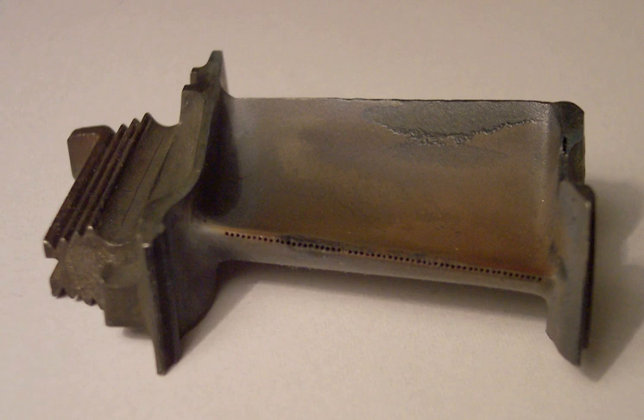The chemical additions of aluminum and titanium promote the creation of the gamma prime phase. The gamma prime phase size can be precisely controlled by careful precipitation strengthening heat treatments. Many superalloys are produced using a two-phase heat treatment that creates a dispersion of cuboidal gamma prime particles known as the primary phase, with a fine dispersion between these known as secondary gamma prime.